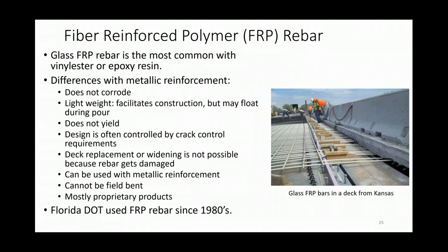The other thing to be wary of is that these FRP bars, glass FRP, can get damaged easily during demolition or concrete removal. So that makes it pretty much impossible to replace a deck or widen it. But there were some workarounds for that. So for example, some agencies reported using steel metallic rebar towards the ends of the bridge, or the sides of the bridge, I should say.